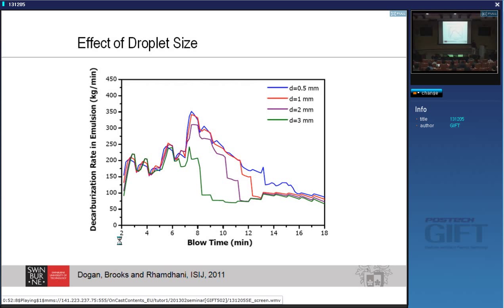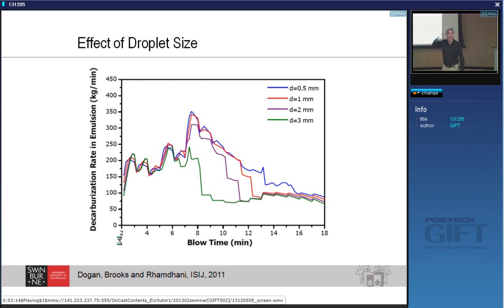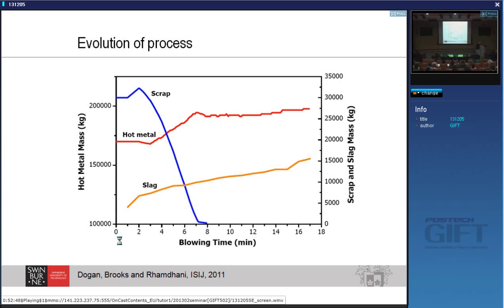When you have a model, you can play thought games, you know, you can play thought experiments. So I went, oh, well, what would happen if you made the droplets very small? What would happen if you made really tiny droplets? And this shows you the impact of the different droplet size on the decarburization. So that's one of the other benefits of having a model. You can start playing thought games. Like, what happens if we blow out faster this way? What happens if we make the lance go deeper? What happens if we add more flux? Etc., etc. And along the way, we've learnt lots of things about scrap, slag formation, and hot metal.